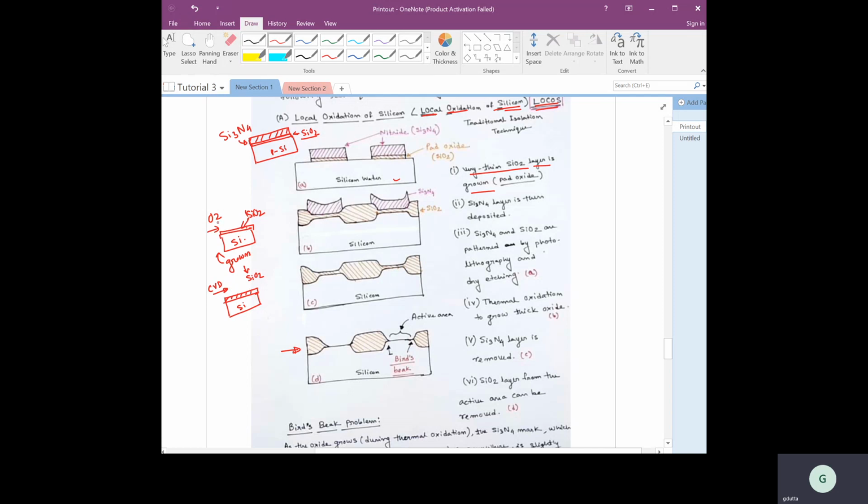So you understand my point, right? So as a result, during this process, when the silicon dioxide is formed, the thickness of the silicon layer gradually reduces, because you are consuming the silicon to form the silicon dioxide. But here the silicon thickness will remain the same, because during this deposition it is not consuming any silicon from here.